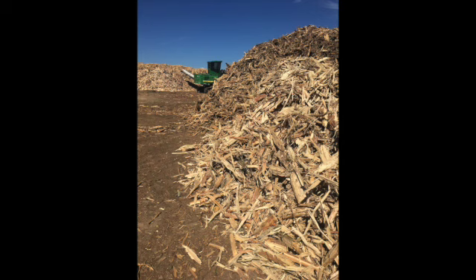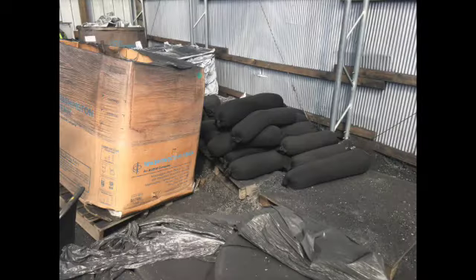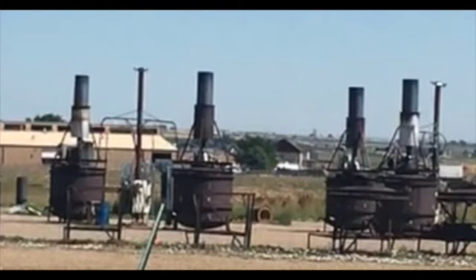A little more than a ton of wood feedstock produces 500 to 600 pounds of very high carbon biochar that is remarkably adept at absorbing cations, anions, and apparently even PFAS, the polyfluoroalkylated substances, or forever chemicals. These kilns use a 14-hour anaerobic cooling period rather than water quenching after a burn. There is an effort underway to extract wood gas from these kilns to run an electric turbine, and the biochar potentially could feed a coal-fired electric plant.